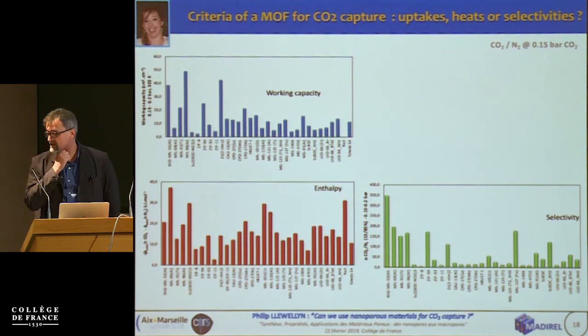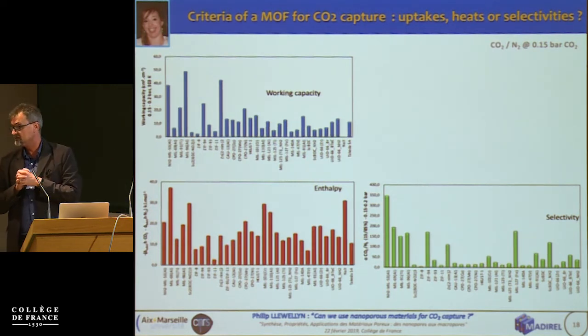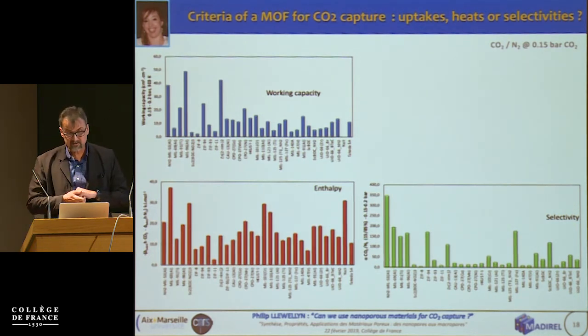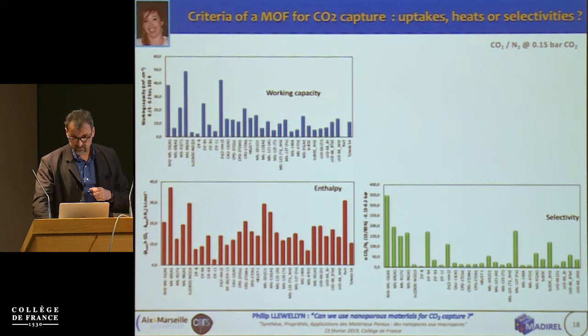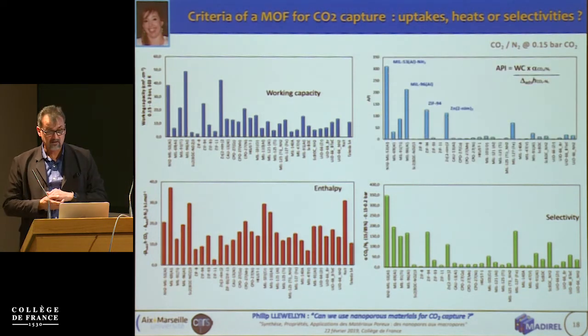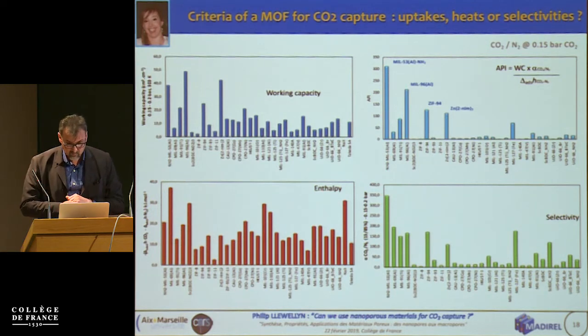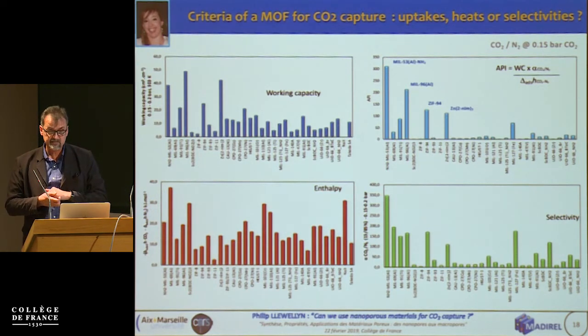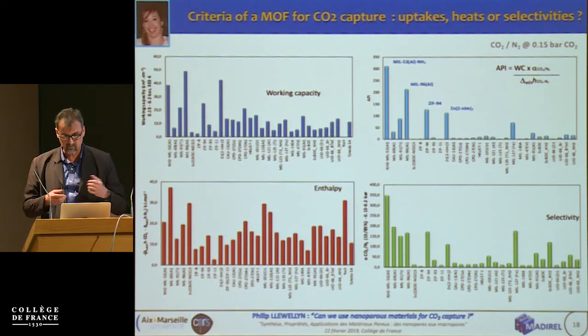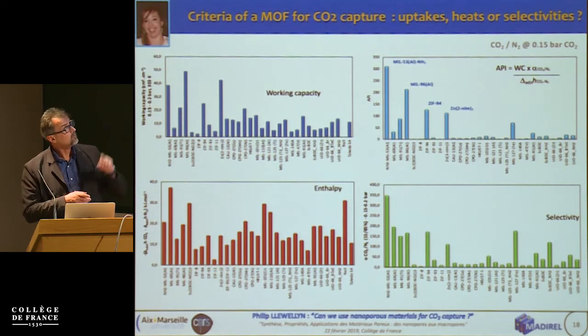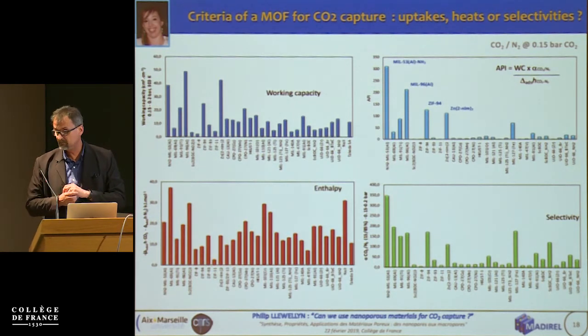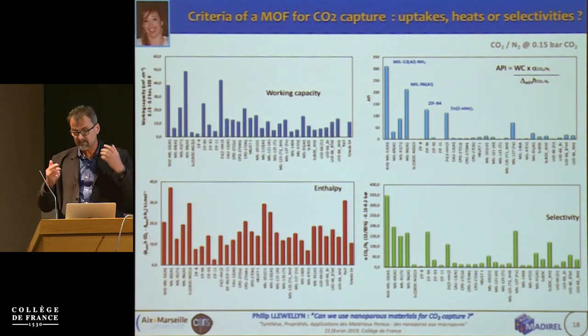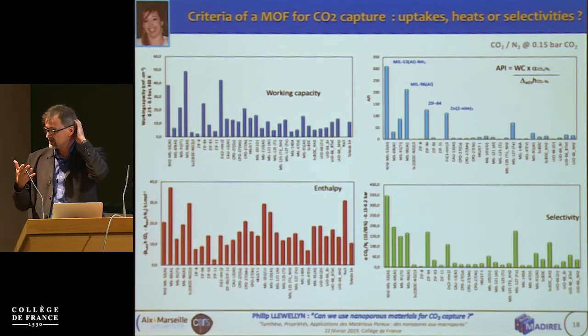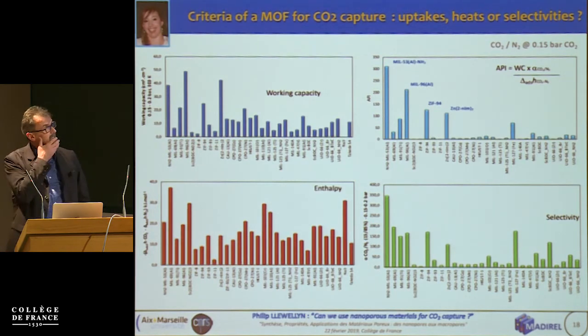The problem now is we've got these three different key parameters. We don't know which material to choose. Do we want one with a really high working capacity, but we're prepared to have poor selectivity? How do we do this? So what we did with a former PhD student is just come up with a formula, which is up here on the right-hand side. We've taken the working capacity, multiplied it by the selectivity, and divided it by the energy, because the heat that we've measured, or the enthalpy, we want to be as low as possible. What is not on this formula here is that we've put in exponents as well, which means that, for example, if you want something which has a really big working capacity, we can have this squared. And this helps us choose a bit more.